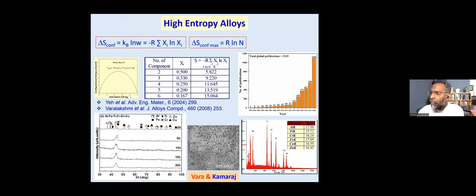So at the center of the phase diagram, typically you have the highest configurational entropy. And if you try to remain in the center of the phase diagram, but have a multi-component system, then as you can see here, let me just use the pointer. Okay, so as you can see here, the maximum configurational entropy goes by R ln n. R is the universal gas constant, n is the number of elements.